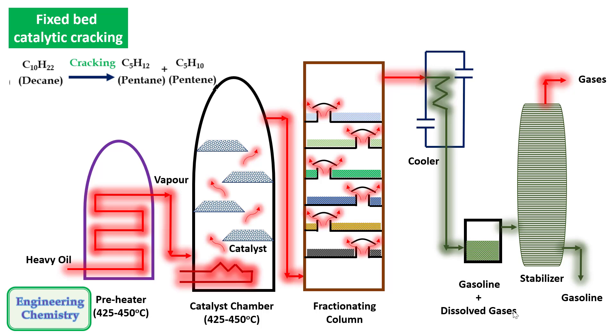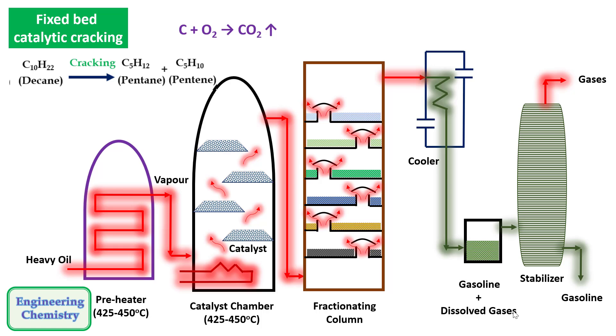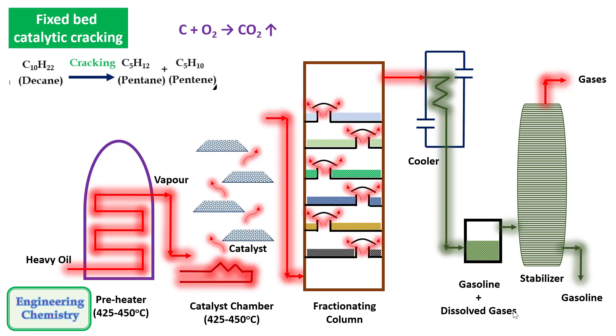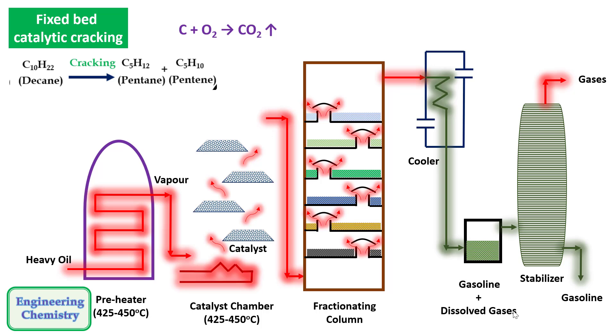After some time the catalyst gets exhausted — its entire surface area gets blocked — and it has to be regenerated. The catalytic chamber is replaced by a fresh one, and the old chamber is heated in the presence of oxygen to convert the accumulated carbon on the catalyst surface into CO2 gas, which is removed and the chamber is regenerated. Two catalytic chambers are used alternately, but this process is very time consuming, and hence it was replaced by fluid bed catalytic cracking.